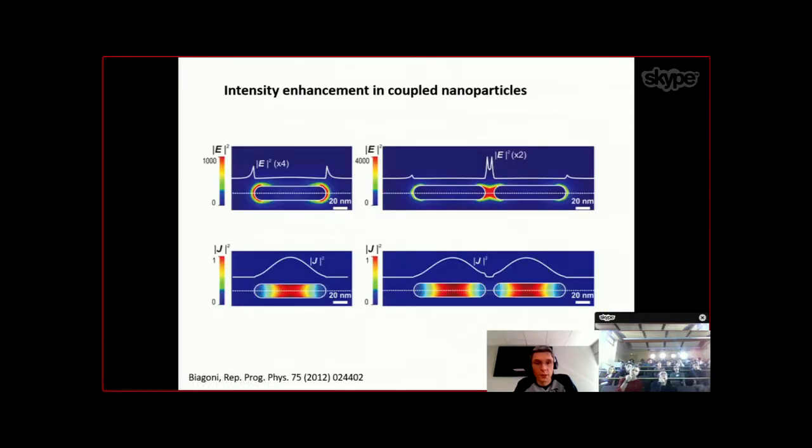Okay, numerical simulation, we find this again. We had the nanorod before, with a peak of 1,000. Now we couple them, and locally we can increase it even higher. Even this is a gap about 15 nanometer. We go to 4,000. So there's a local increase, and this is the illustration I gave you in the introduction motivation part of this talk. Light is concentrated on a spot that is on the orders of tens of nanometer. Okay, and it's pretty much intense, much more than the incoming light.